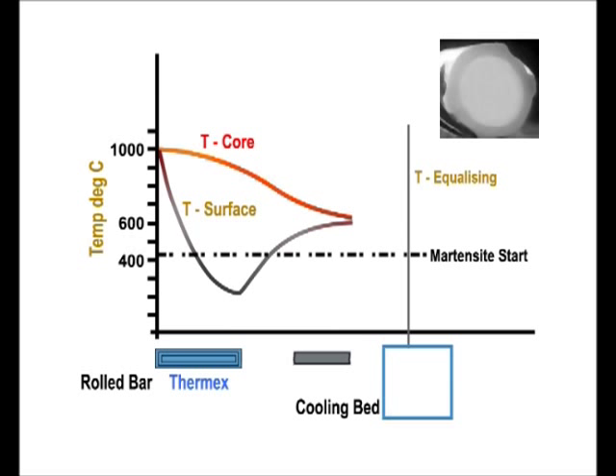The water quenching results in drastic surface temperature drop, resulting in a uniformly hardened periphery with a soft, ductile core. On leaving the Thermex pipes, the bar gets further cooled in atmosphere.